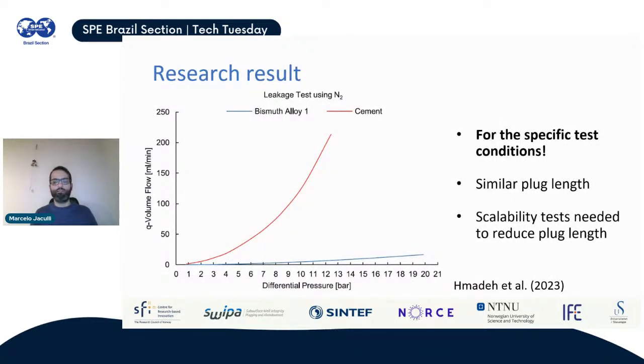So in this literature review, we put some very preliminary results that we achieved by performing some leakage tests with nitrogen gas, and we had plugs of similar length of bismuth and cement, and we saw that the leakage rate through the bismuth was much lower than it was for the cement. But of course, I have to put a big emphasis here that this is applicable for that specific test condition. You can find more details in the publication that I mentioned at the beginning.